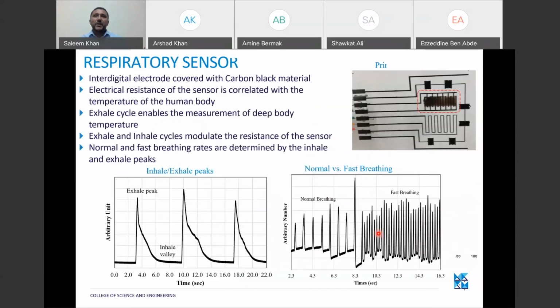Similarly, for the respiratory sensor, we are exploiting the temperature of the exhale and inhale peaks that we can utilize in the smart mask. Simultaneously, we are able to record the human body temperature, and from the inhale and exhale, because there is an instantaneous change in the temperature, these peaks can be correlated to normal or fast breathing. Here are the tested results in the lab using this sensor patch, which was developed using inkjet technology.